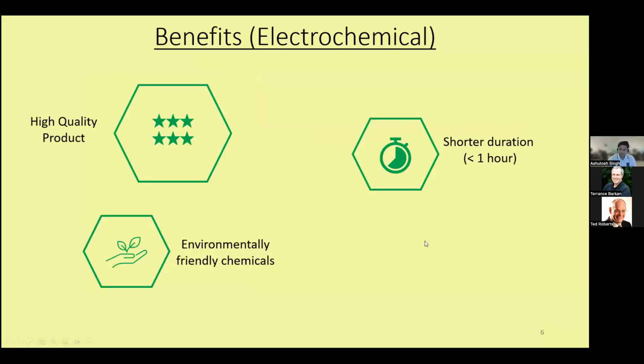During the course of this technology development, we observed several key benefits of this process. The first obvious one was the high quality product. By high quality, I mean quality in terms of the thickness of the graphene. Since you are able to better intercalate under the action of the electric field, you are able to better control the intercalation process. This ensures that you are peeling the layers more accurately, and hence you are able to generate more single layer, double layer, and triple layer graphenes. That really brings value to our customers or any other application developers looking for such high quality graphene.